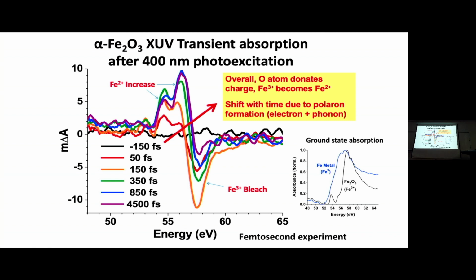And now, however, if you stare at this data for a little while, you realize there's something more. If everything were just 3 plus goes away and 2 plus appears, they should kind of all reach a point here, but instead there's a shift going on. And this shift was very confusing for a while, and a lot of people in the group were working on it. And what we realized at one point is that it's probably due to what's called a small polaron formation. That's where you trap an electron by a phonon, by a vibrational mode in the solid.